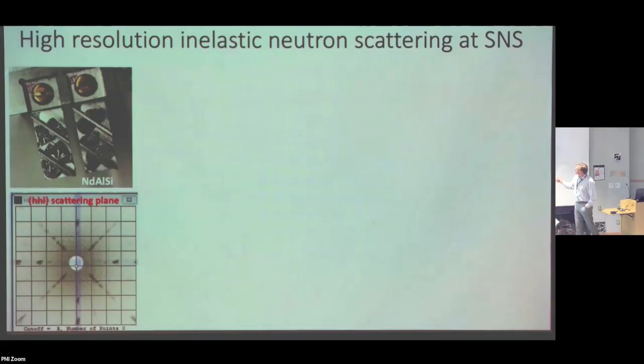And so this was again a situation where you cannot grow big crystals of high quality of this material. We have tried. Our colleague Said Copier has tried, but it seems that the flux growth is really the best way to get at the crystals. But those are very small, so you assemble many of those together, and this is how that's done.